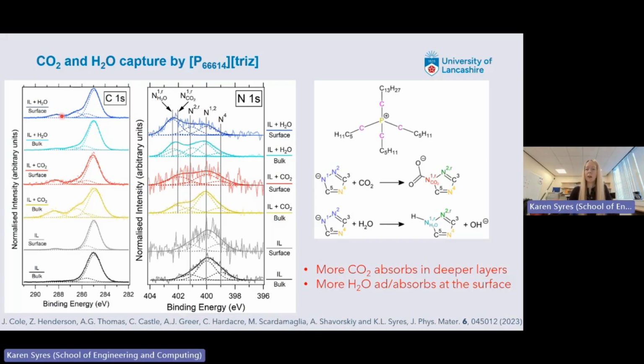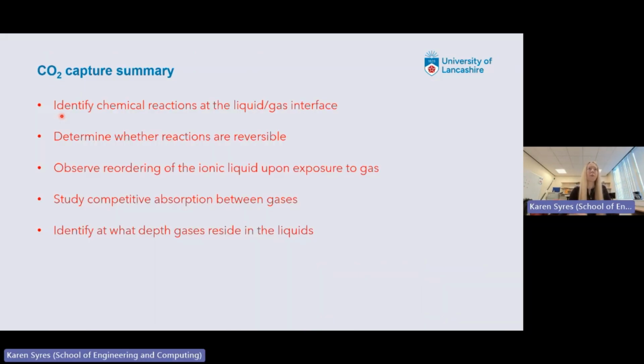So from our measurements, this is just a little summary about my research into CO2 capture. Using the techniques that we use, we're able to identify chemical reactions at our liquid gas interface. We can determine whether they're reversible. There's another technique that we do where we can work out how the ionic liquid orders. So we discovered that when you expose it to gas, the molecules in the ionic liquid kind of reorder themselves as the gas goes in.